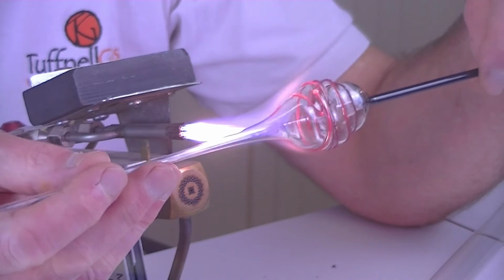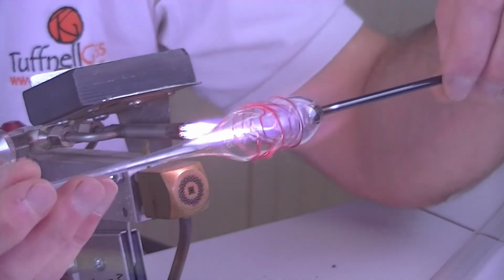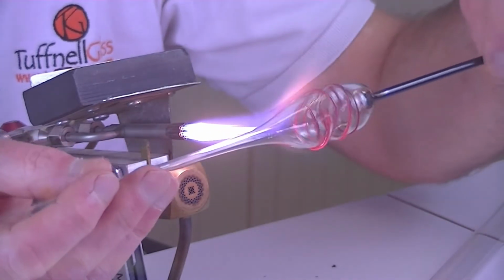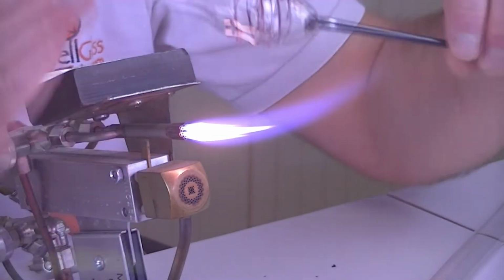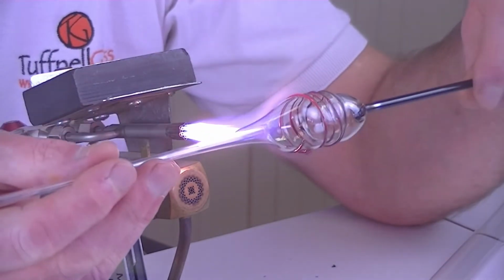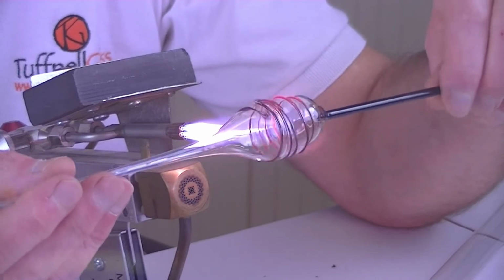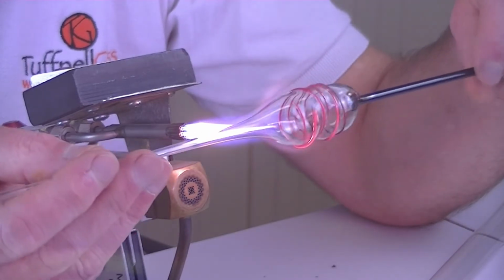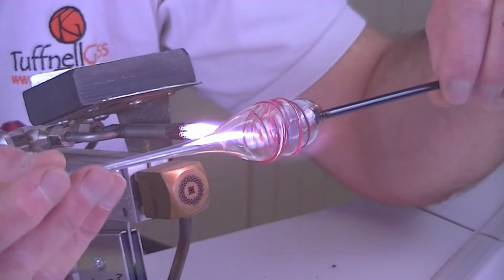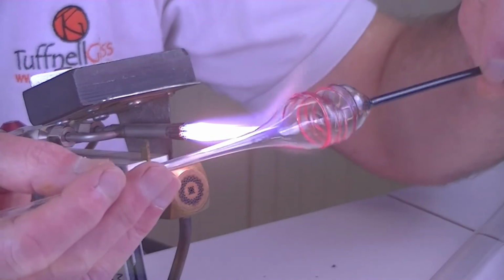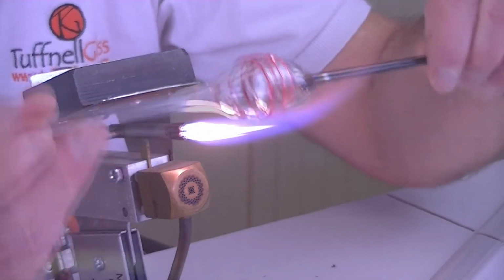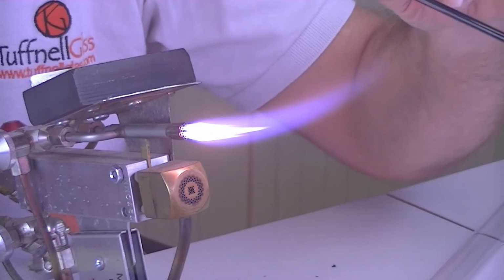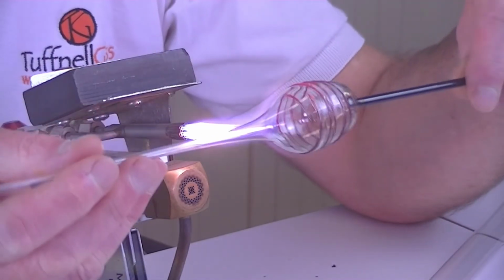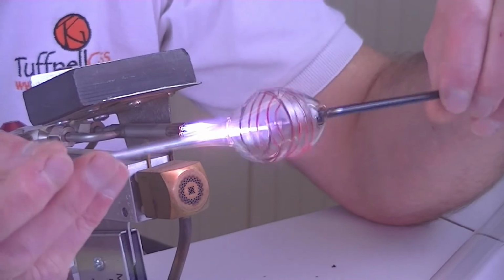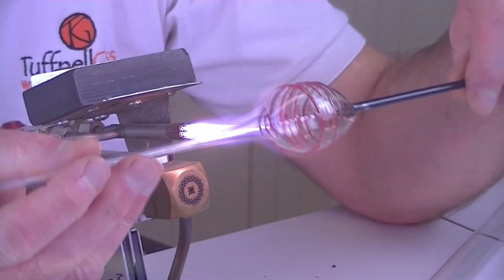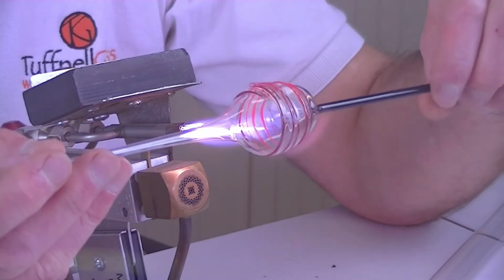And if it starts to pull towards itself, so if you imagine the point was originally 1.5 inches long, and now as it starts to shrink, it comes back to sort of like 1 inch, that's fine, because the glass wall is thickening up, and that's ideally what you want. So that if you get to a couple of millimeters thick, as you blow it out, it only goes down to 1 millimeter instead of 0.5 millimeter. And so you've got a lot of strength still there.